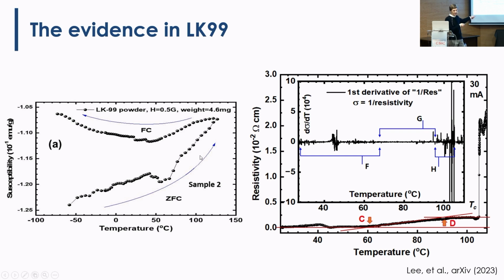I never plot these figures in centigrade. We all use the Kelvin scale, but here it's centigrade. And this transition coincided with a drop in the resistivity. You see that the resistivity they were measuring was dropping at a similar temperature. So that's why they thought, wow, we found that.